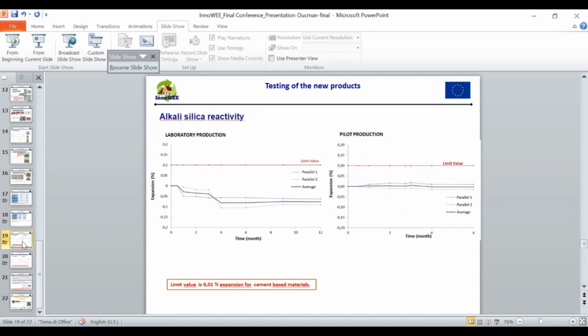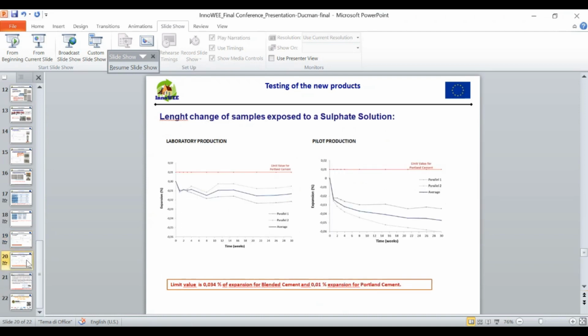There, more detailed data are graphically presented for alkali silica reactivity and for sulfate attack. We can see here the limit value set for cement-based materials, and we can now compare results from the pilot production for 1 year and from the laboratory production for 1 year. For pilot, we have only 6 months because we received samples later, but still we can see that the results are very similar, so there is good agreement between laboratory and pilot production. The same can be said for resistance to sulfate attack. Values are far below the limits for cement-based materials, and also here the trend for laboratory production and the trend for samples from pilot production are practically the same.